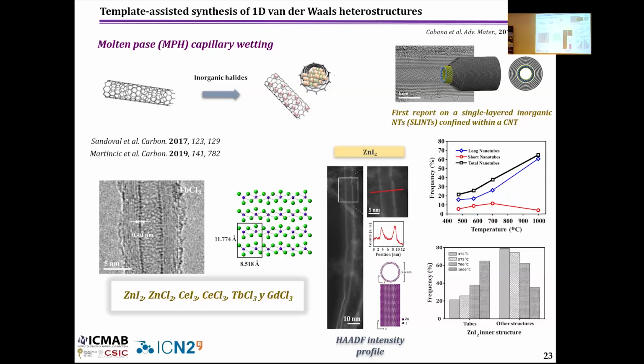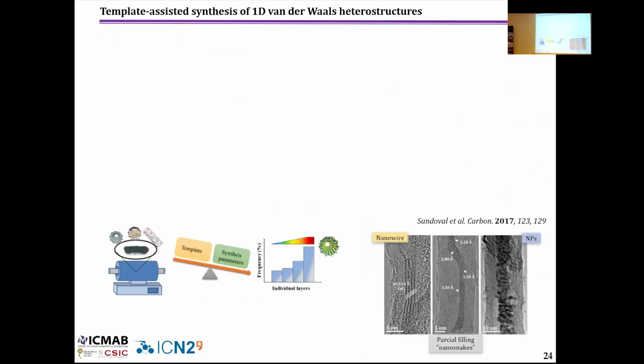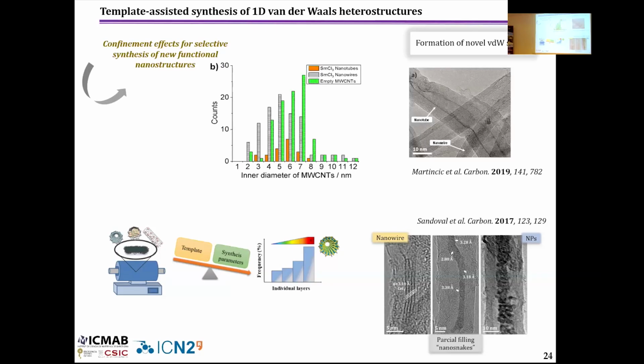So in this case, we use different temperatures, different conditions in order to improve the possibility, reaching up to 60% of nanotubes against other structures by increasing the temperature of treatment. But of course, there were still other nanostructures present inside the nanotubes. So, yes, confinement.